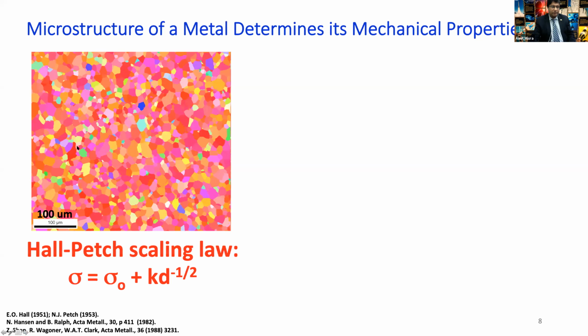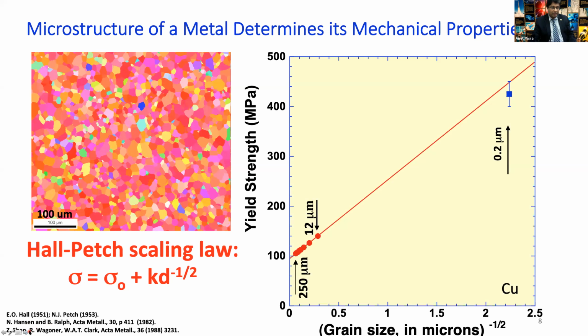And by this model known as the Hall-Petch scaling law, it is known that the yield strength of this microstructure will scale with 1/square root of the average grain size. And so using that, we can get an idea of what the strength of a metal will be. This is an example for copper. If you plot the strength against 1/square root of the grain size, you get a linear relation with the slope of K, which is the Hall-Petch slope. And you get a sense of what the strength numbers will be, typically on the order of a couple hundred megapascals if the grain size is on the order of tens of micrometers, which is where most typical metallic microstructures are.